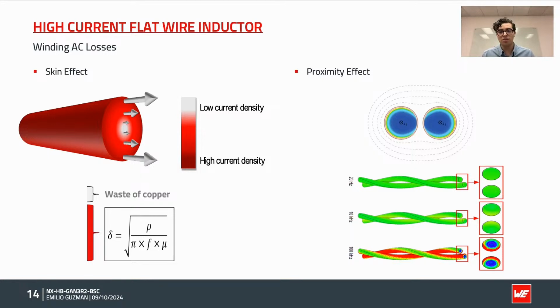As for the winding AC losses, the skin effect and proximity effect are also a key factor to take into account when choosing the type of wire for the inductor. For the skin effect, when frequency increases, AC tends to flow near the outer surface of the conductor, rather than uniformly throughout its cross-section. And as the effective area for current flow decreases, resistance increases, thus increasing the losses. Here, a flat wire improves on this, with its geometry helping distribute current more evenly and reduce losses at higher